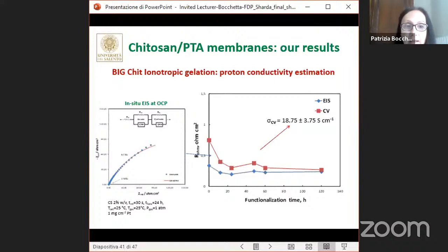We have also estimated the membrane proton conductivity by in situ electrochemical impedance spectroscopy performed in the single fuel cell fed with hydrogen and oxygen at 25 degrees centigrade and at open circuit potential condition. It can be observed that the values of proton conductivity are consistent with those obtained by analyzing the fuel cell polarization curves in the pseudo-linear part of the curve. You can see from the figure that the proton conductivity increases as the post-cross-linking treatment time increased to 60 hours and then slightly decreased at 120 hours, confirming the previous results.